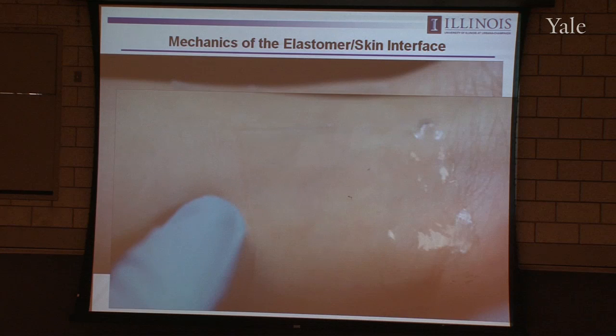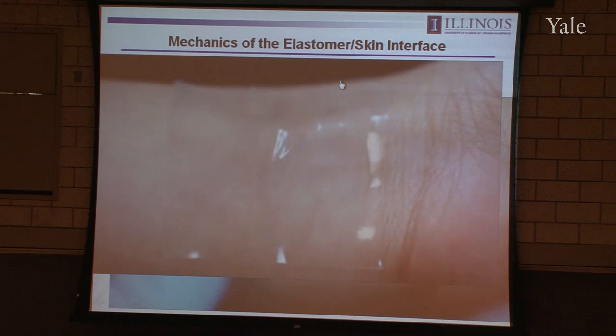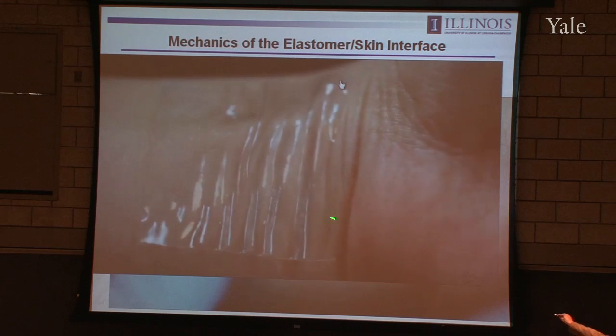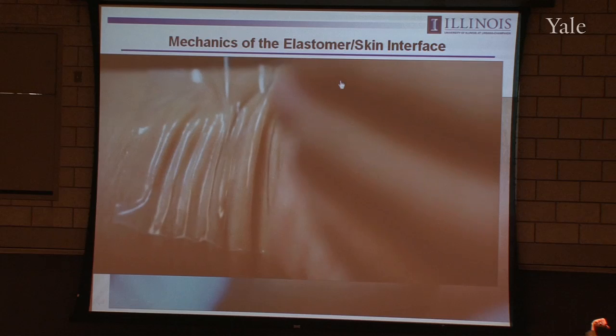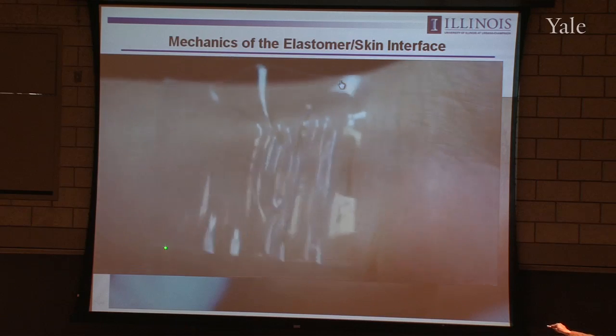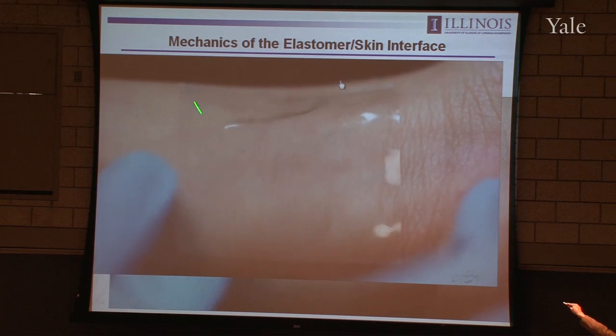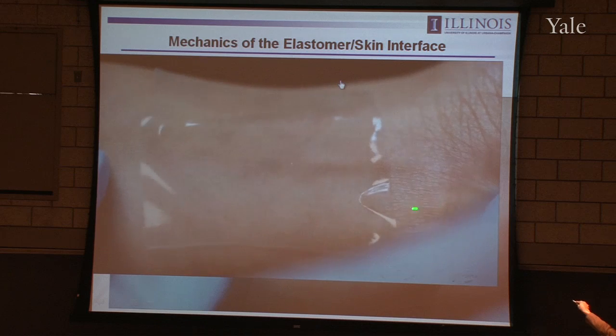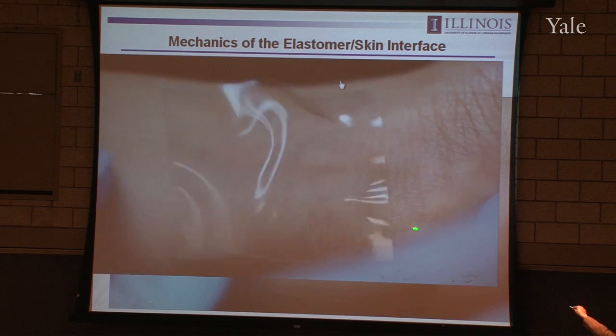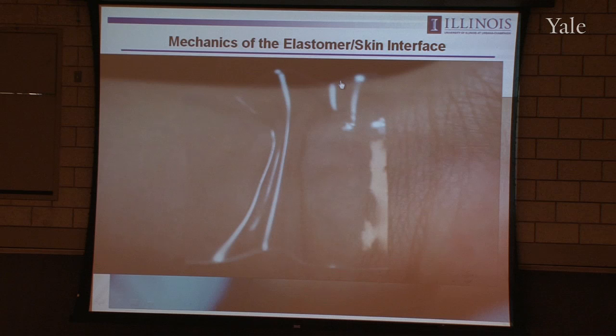And you can kind of see that physics here. So if you just take a sheet of rubber and laminate it to the surface of the skin, you can see the effects of thickness and modulus even when the materials are exactly the same. So this is on the arm of a postdoc. It's a sheet of silicone rubber. Here it is laminated, and then the wrist is being contracted like that. And you can see you start driving delamination at the edges. The thing just flakes off. If you stretch it like this, again, edge-initiated delamination, the sheet comes off.